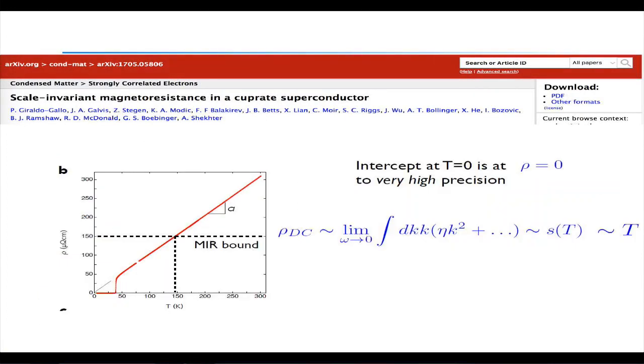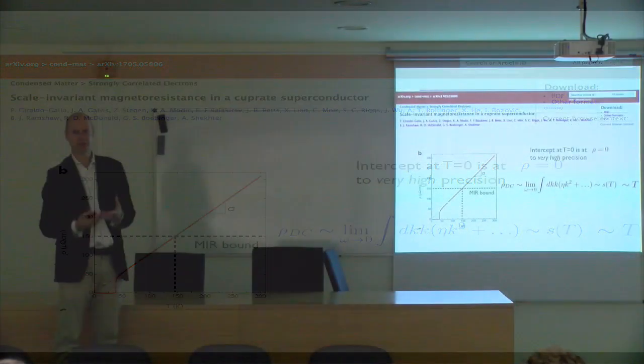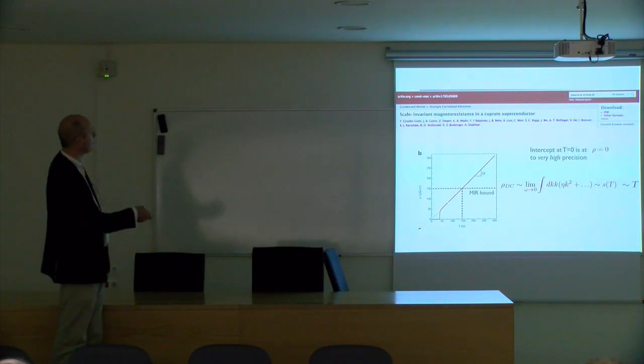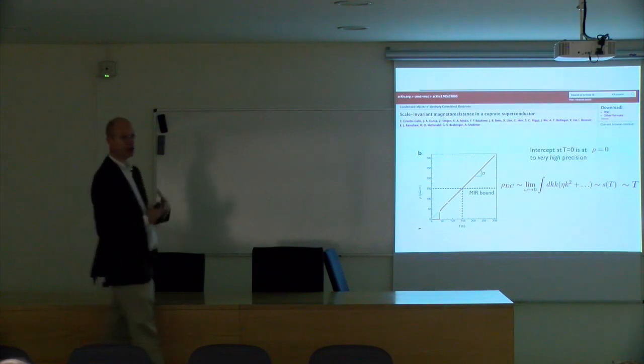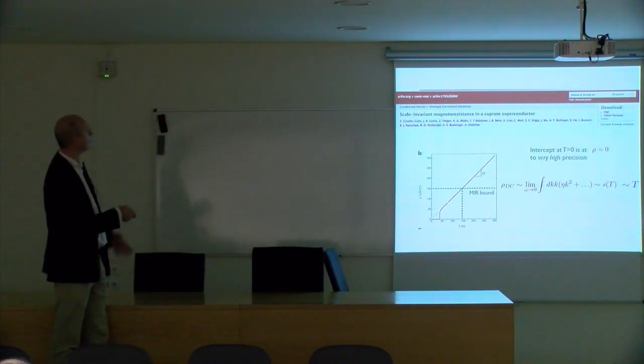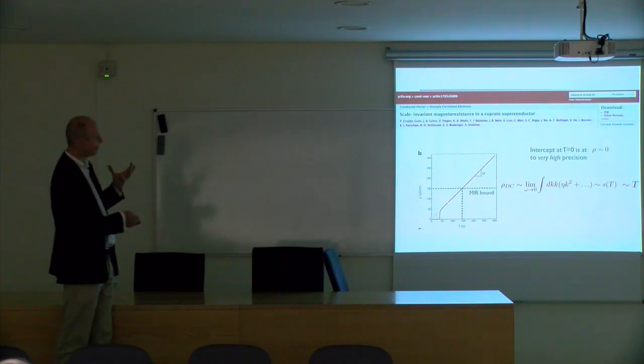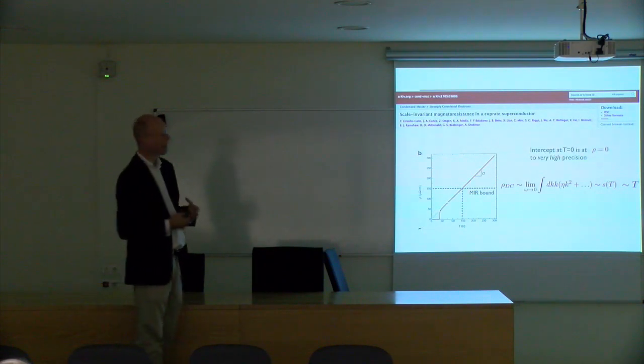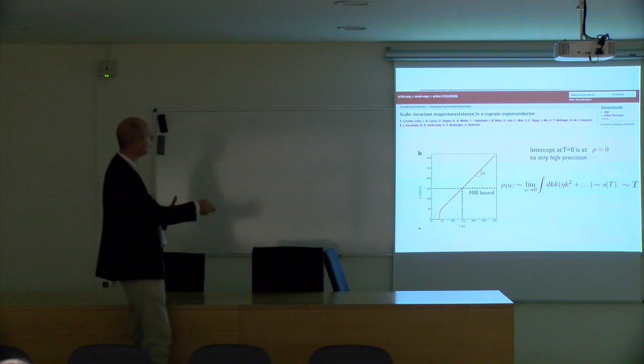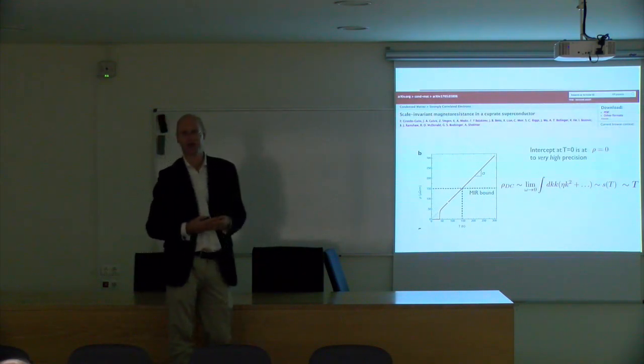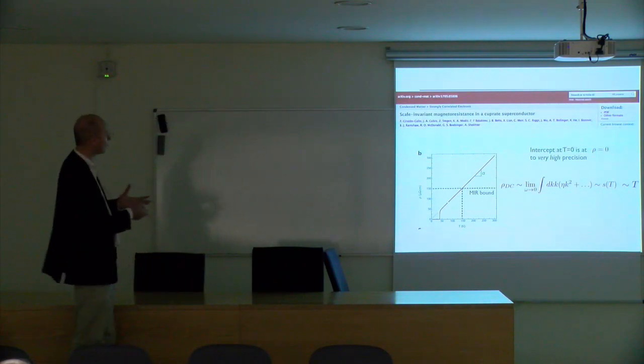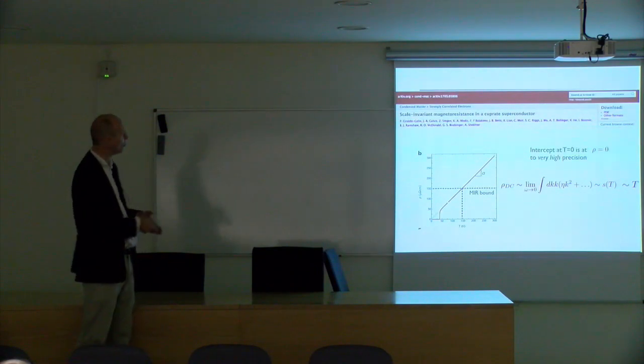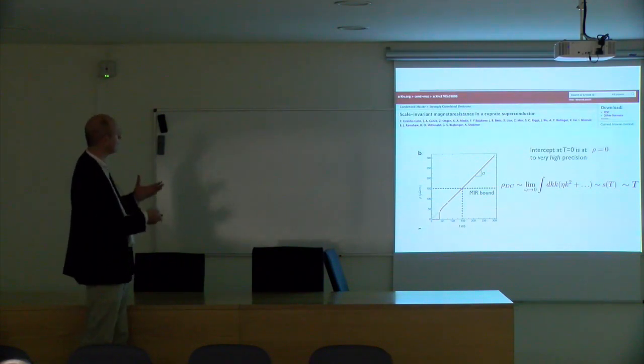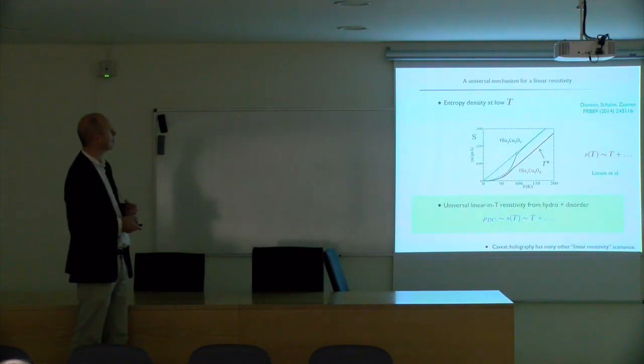One is that if I look at the resistivity, because the resistivity is proportional to entropy density, and entropy density is proportional to T, and thanks to the third law of thermodynamics, we do not expect remaining entropy density at zero temperature, it means that if you extrapolate this line down to T is zero, it should cross precisely through the origin. And this is a recent result from 2017, and indeed, when you read the paper, they see exactly this. They can't really go all the way because superconductivity sets in, but if you extrapolate all their data, it goes through zero to very high precision. This is indicating perhaps something interesting is going on. Normal metallic systems always have a residual resistivity, even at zero temperature, but this seems to indicate there is none.